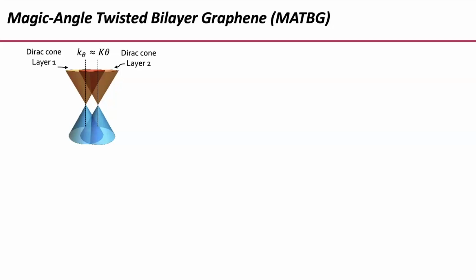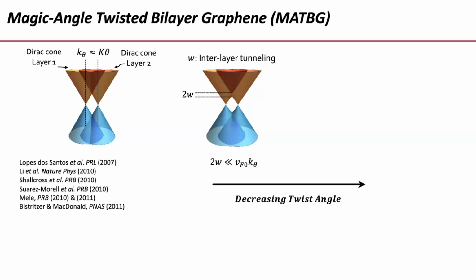However, because when we place graphene on top of graphene, these two graphene sheets are just 3 angstroms apart, electrons are very much aware that the other graphene sheet exists, and in particular, they can tunnel between the two graphene sheets, okay? That interlayer tunneling leads to band repulsion there at the energy of that crossing point. This is the same as bonding and anti-bonding states for the hydrogen molecule, but this is bonding and anti-bonding bands for this bilayer graphene molecule. Okay? And this is the situation when this interlayer tunneling is much smaller than the energy of that crossing point. But if you decrease the twist angle, at some point, this lower band that gets pushed down in energy gets pushed down all the way to 0.